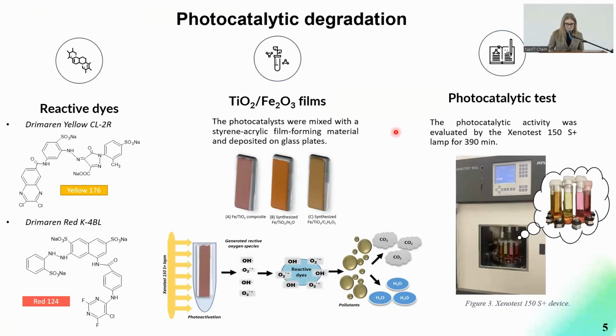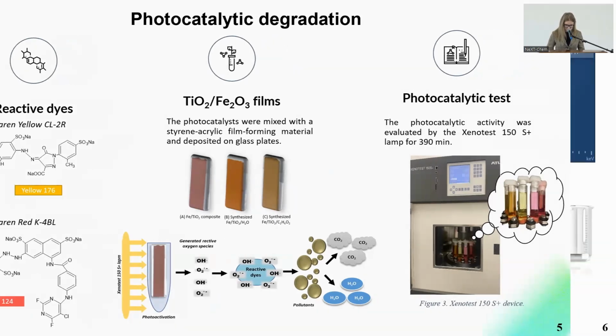For the photocatalytic degradation, it was carried out using some basic reactive dyes, such as Drimaren yellow, color index 176, and Drimaren red, color index 124. The paint formulation was provided by King Color. For this purpose, the photocatalysts were mixed with a styrene-acrylic film-forming material and deposed on glass plates. The photocatalytic activity was evaluated by xenotest lamp for 390 minutes.